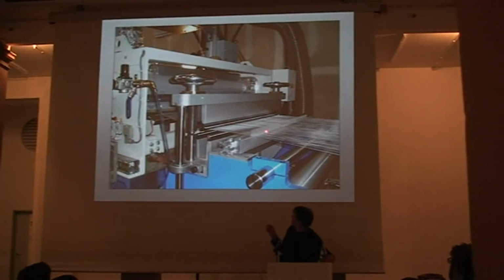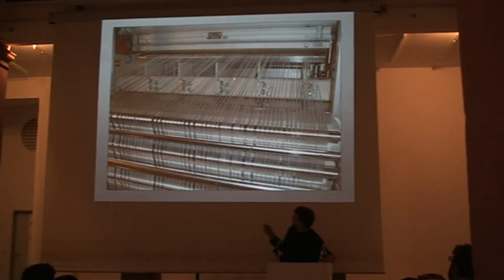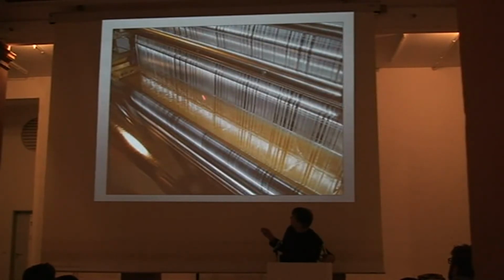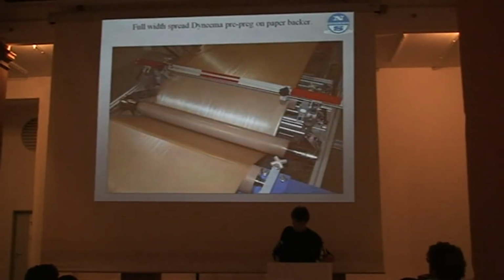You can see the yarns or tows running into one side of the head. Here they're coming out the other side of the head, and they're starting to spread out here. So it's a yarn or a bundle of filaments up here, and you can see it's starting to flatten out into the individual filaments. And here it goes into the resin bath, and the yellow stuff here is just resin. And you can see they're spreading out and are almost in tape format now as they go into the resin, and the viscosity of the resin finishes the spread out of sight. And we make this 600 millimeters wide.